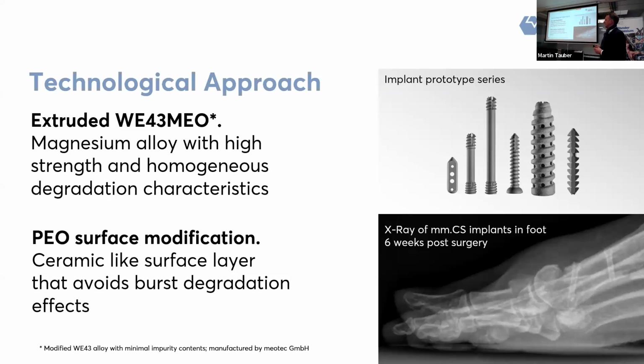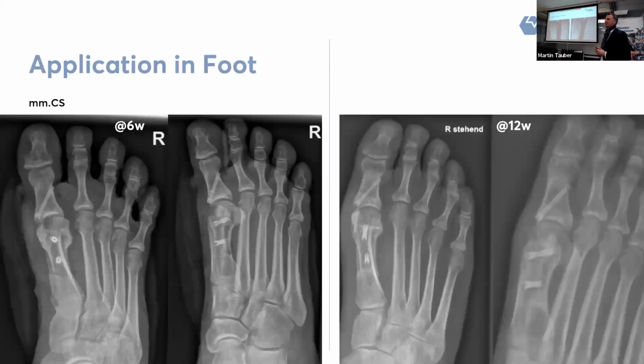All right, and with this, I'd like to show you some images from our lucky customers, some X-rays, and some different application sites for our implants. So in this case, we see the application of our compression screws in a foot, and you can see the fracture line, which was right here, seems to close over time. So we can compare the 6 weeks and the 12 weeks group here. So basically the job of these implants is done here, and the degradation can just simply progress until the implant's gone and until it's being replaced by bone.